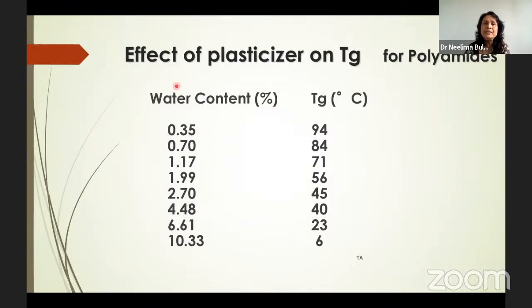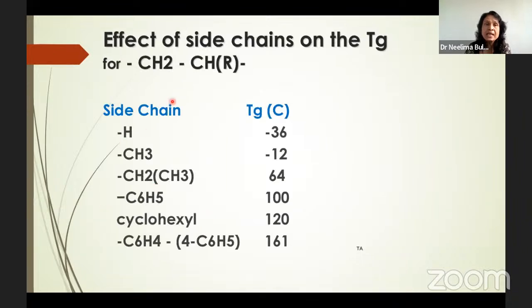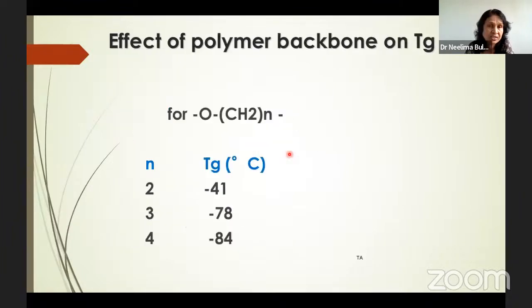Plasticizers. Nylon samples, we know, are going to absorb moisture, and if you increase the moisture content, TG varies from 94 degrees centigrade to 6 degrees centigrade. Again, a variation of around 90 degrees centigrade because of just an increase in the moisture content. Similarly, side chains. If you increase the number of bulky side chains, the TG increases from -36 to 161, because here I'm having 2 benzene rings, and with one hydrogen I'll get -36 degrees centigrade.